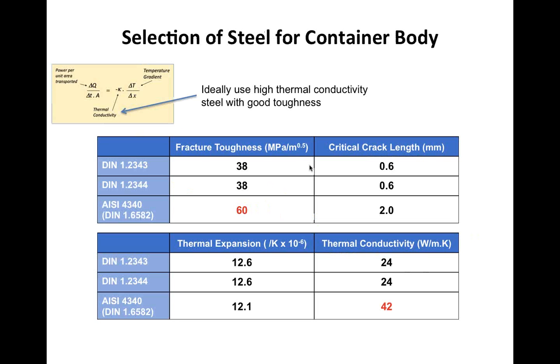And if you pick the right steel for the container, in this case, we would like to see the steel that's being used has high thermal conductivity coupled with high toughness. And so the choice comes down to AISI 4340 steel. It has 60 megapascal of fracture toughness and 42 watts per meter per Kelvin for thermal conductivity. That is almost double the thermal conductivity of typical material we see in the market, H13 or 1.2344, and also double the toughness of 1.2344 or H13 materials.